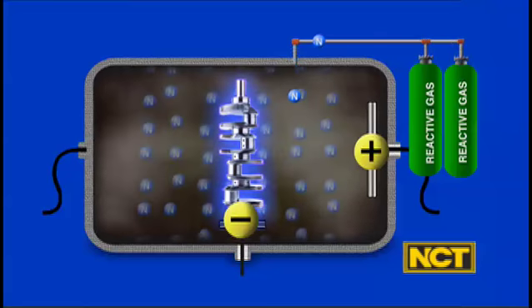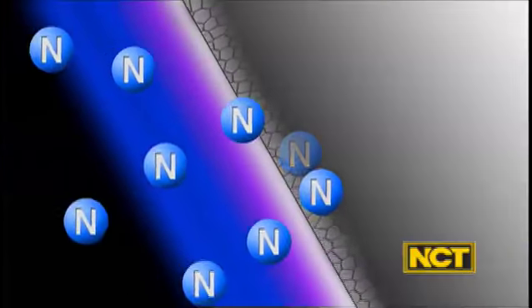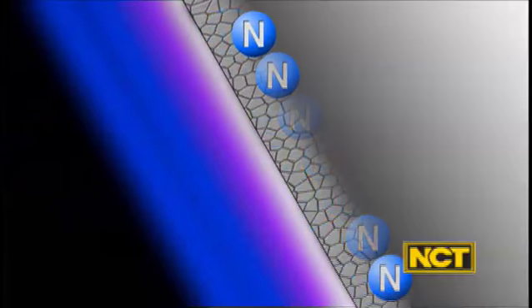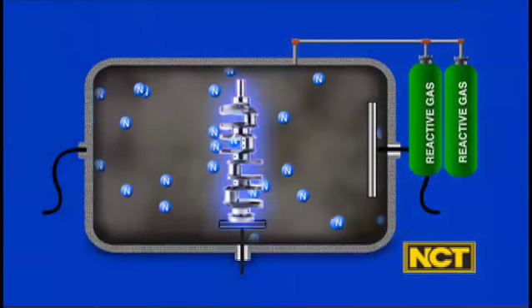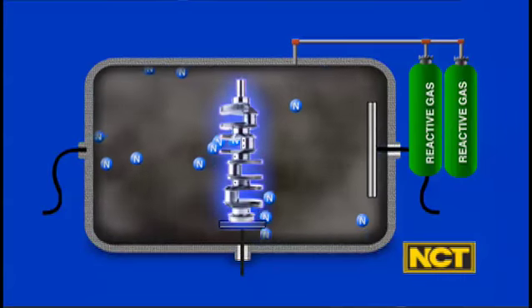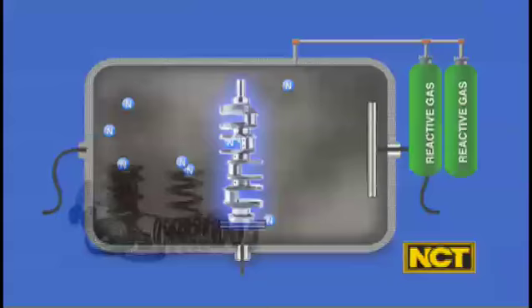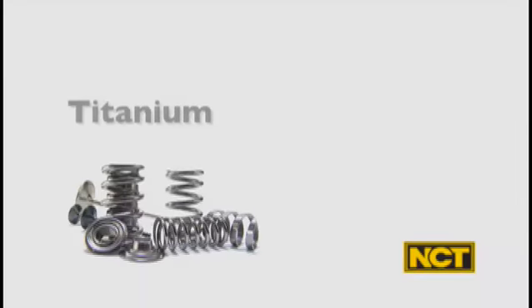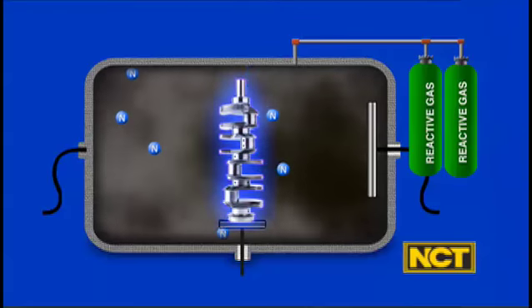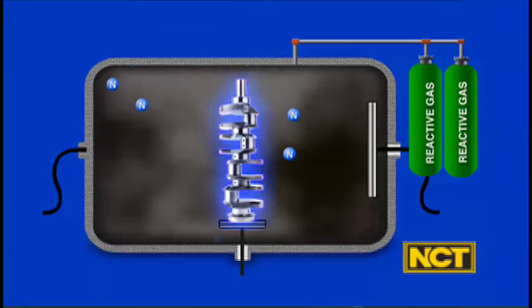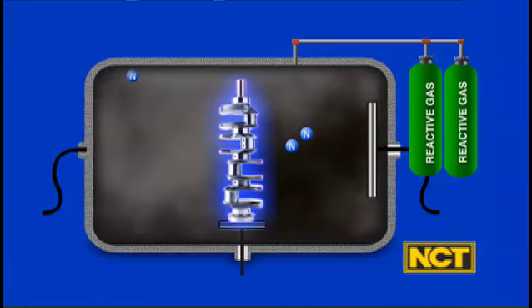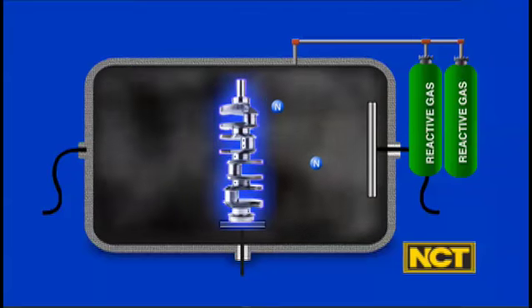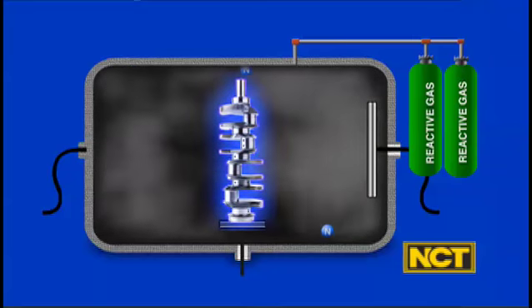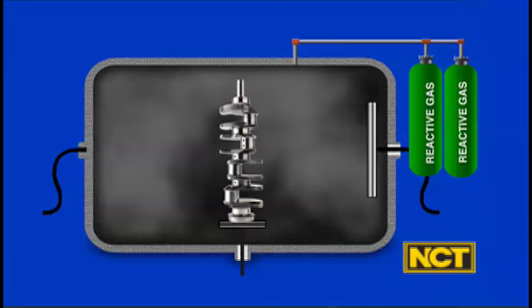The nitrogen present reacts with the iron in the steel to form a compound layer of iron nitride on the component's surface. This surface layer is the supply for the nitrogen to diffuse into and react with the nitride-forming elements in the component, which include chromium, titanium, aluminum, or vanadium. A constant supply of the gas mixture is fed into the chamber to sustain the nitriding process and produce a uniform case depth. When the designated processing time has elapsed, the plasma is extinguished and the product is allowed to cool.